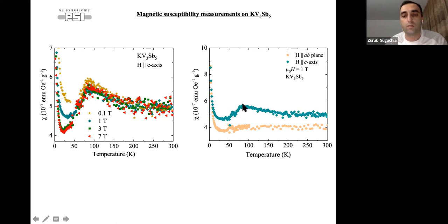And this could also maybe be related to orbital currents, because the orbital currents are coupled to the c-axis moment. They don't really create much internal in-plane fields. And maybe that's why the effect is stronger when the field is applied along the c-axis. At least the fact that the magnetic response is really anisotropic maybe points to the fact that there is some magnetic origin coupled to the charge density wave transition.